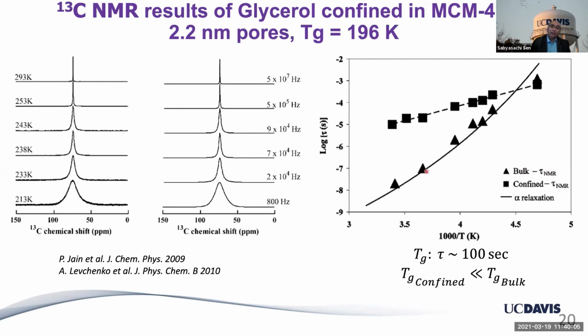Okay. In contrast, this is the data we got for the confined liquid, okay, which shows that this is very, very slow at any temperature until you get to a much lower temperature where there seems to be a crossing, but within error that could be disputed. We could not go any lower in temperature, but at least in this temperature range, it seems like it is not only Arrhenius or strong behavior with a single activation energy that is temperature independent, unlike bulk, but also it's very, very slow moving in nanospace. At high temperature, the difference could sometimes be 3 orders of magnitude in the time scale.